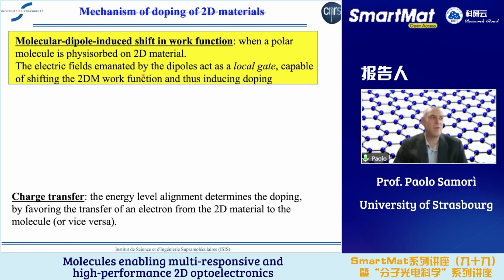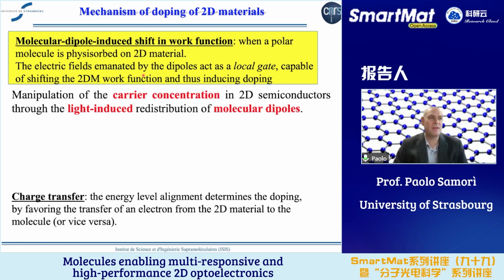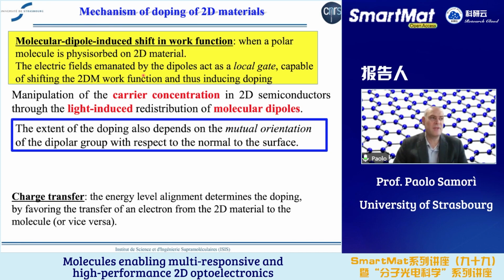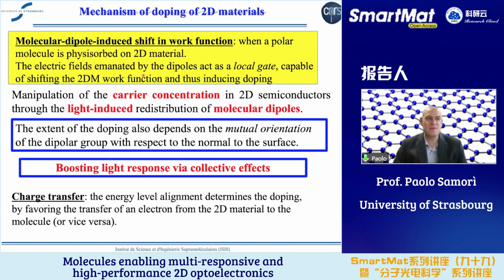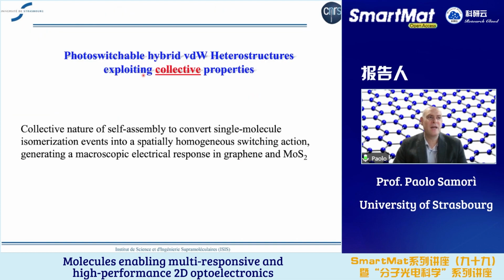So let's start to see how molecular dipole-induced shift in the work function can be used to manipulate the charge carriers by a light-induced distribution of the molecular dipoles. The idea is that if you want to play with dipoles, the magnitude of the doping depends on the mutual orientation of the dipoles with respect to the surface. And therefore, you can boost this effect by using collective effects and being able to align all the dipoles. This collective effect by a molecular sorbate is very similar to what you have in van der Waals heterostructures. So we are fabricating nothing else than inorganic-organic hybrid heterostructures.